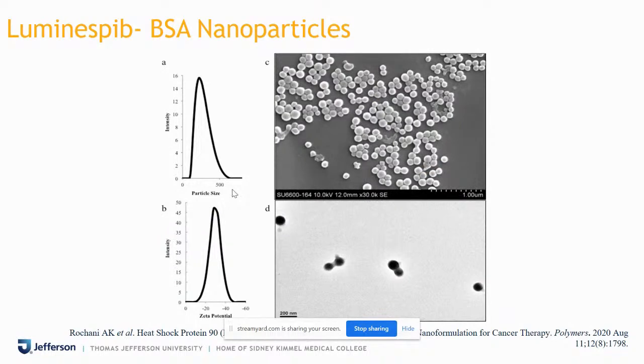The structure of these nanoparticles was confirmed using dynamic light scattering. As you can see over here, the A panel shows the particle size distribution from 0 to 500 nanometer. The average particle size was approximately 220, if I'm correct. It's already there in the published literature. And the zeta potential was also negative.